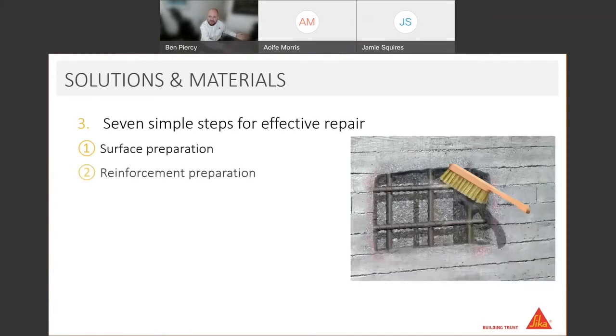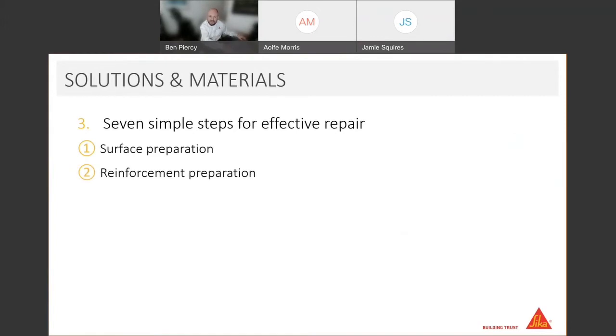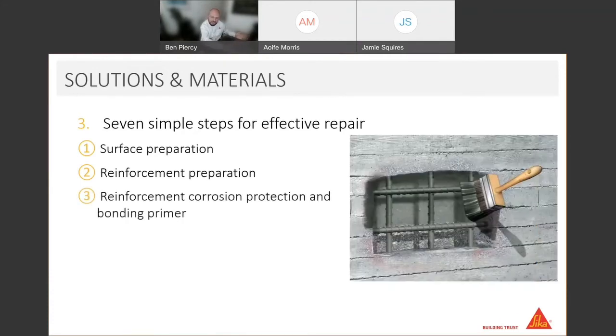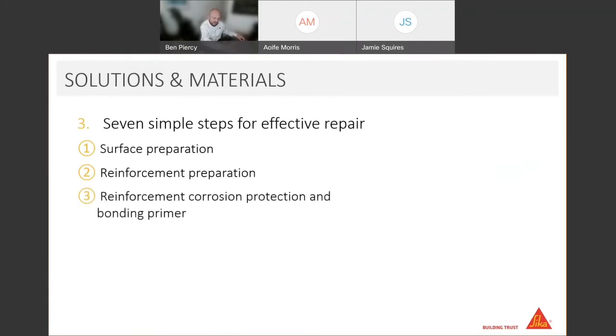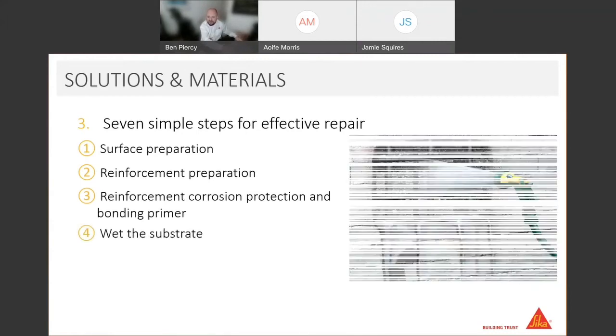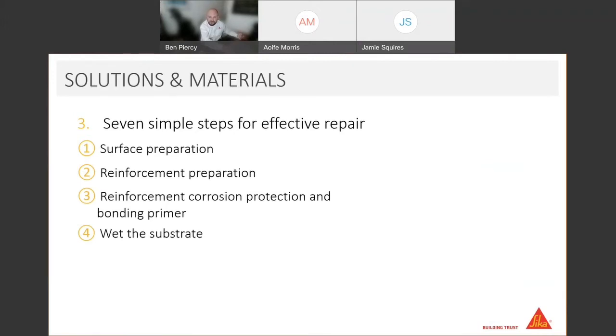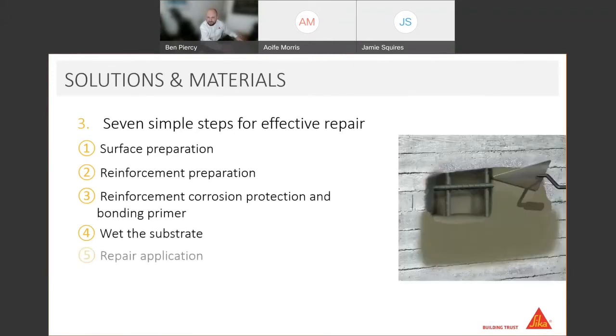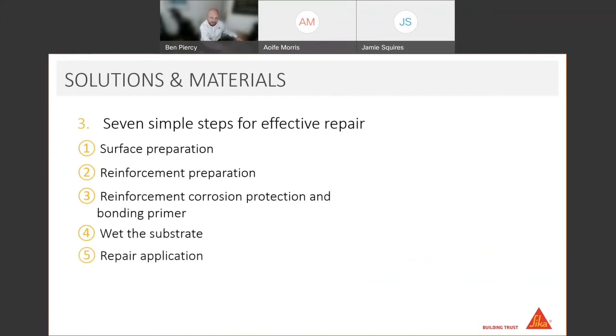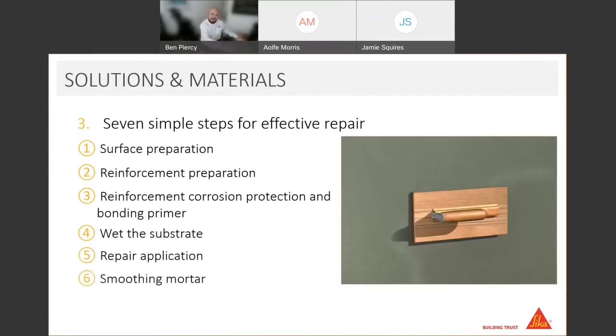Surface prep: we never advise the repair to be carried out in the void that you just saw there. Within our specification, alongside council housing clients, we always specify that all the repairs, as you saw on that image there, are broken out at 90 degree angles, with the rebar fully exposed. You will then be ready to accept the first product of our system, which is a bonding primer.